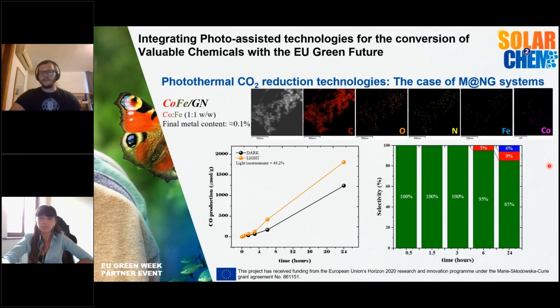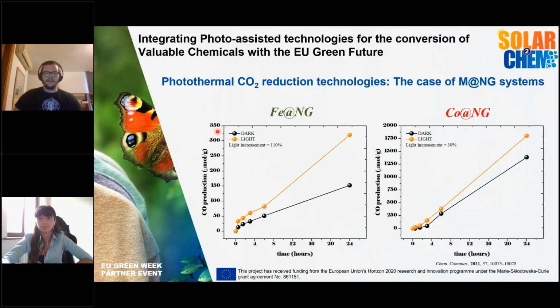The dispersion of the metals and the catalytic support were still very fine, with particle sizes lower than 2 nanometers. So right now we can talk about clusters. And what's even more interesting is that the catalytic output only decreased by half, despite decreasing the metal content by more than 100 times. So this was quite an interesting system that we decided to go very deep into studying.